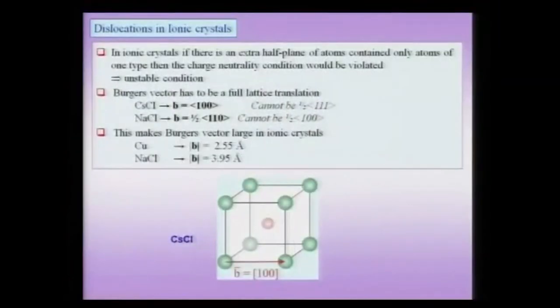And we have to remember, for instance in the example below, the Burgers vector has to be a full lattice translation vector, and therefore, b in this case is 1 0 0 and not the vector connecting the Cs atom to the Cl atom. So, that is not a full Burgers vector. In sodium chloride, which has an FCC lattice, the Burgers vector is half 1 1 0 and it cannot be half 1 0 0, because the Burgers vector connects one lattice position to another